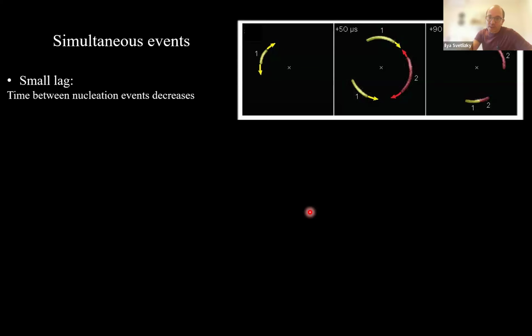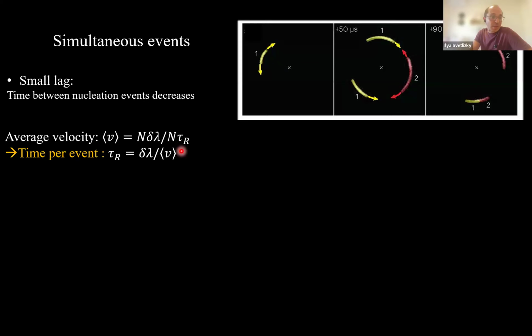When we decrease the viscosity, these are first evidence that you have two simultaneous nucleation events. The first nucleation event happens, and the yellow crack propagates clockwise and anti-clockwise, traversing almost half of the perimeter. A second nucleation event takes place, and these can meet. So when the transition happens from single nucleation to two nucleations and more, it's easy to compare the timescales. You can think about an average velocity of the crack. It's pretty much the average velocity of the fluid, and it equals the number of jumps times the jump amplitude, divided by the number of events times the waiting time between two events, meaning that the time per event is simply the jump amplitude divided by the average velocity.